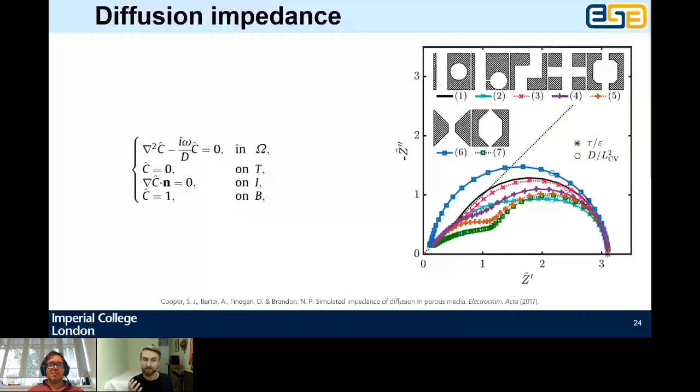So I think it's important to keep in mind that already, no matter how nicely you calculate your tortuosity factor, no matter how brilliant your tomography data is, you shouldn't be surprised if your one-dimensional model does not agree with your actually measured battery impedance data, because it really is a 3D structure. A 3D microstructure will have different performance than 1D, than this kind of homogenized system in many cases.